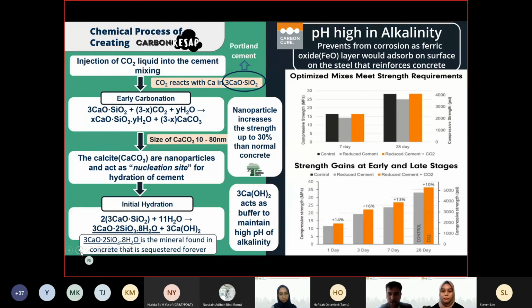Are you wondering what happens after CO2 liquid is mixed with the concrete? Here, we explain the chemical reaction of CarbonCure concrete. It has 2 main stages to be converted to a solid concrete. Firstly, it undergoes early carbonation, where it produces nanoparticles of calcium carbonate. These nanoparticles are 10 to 80 nanometers in size, which act as a nucleation site for initial hydration of the cement.